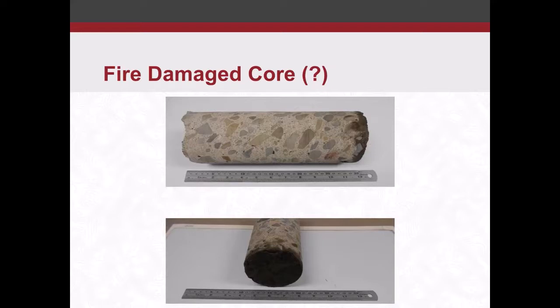So we didn't know if it really reduced the strength or not. I think these cores came up to be over 4,000 PSI, so assuming it was probably a 4,000 PSI mix. I brought these cores back to the office and everybody's gasping at what they see at the end, saying, boy, the concrete really burned up there. Well, that's actually not burned up concrete. As I mentioned, when it gets hot and fire damaged, it usually turns more of a lighter color.